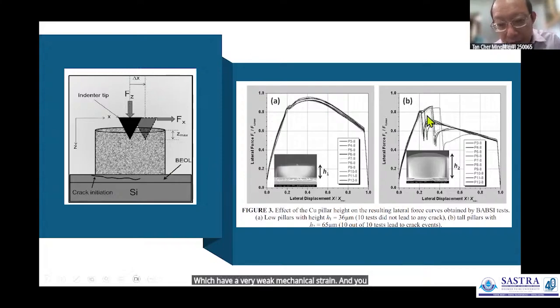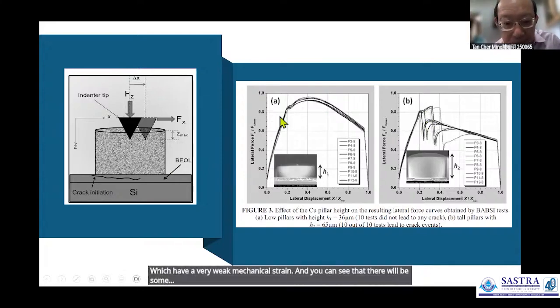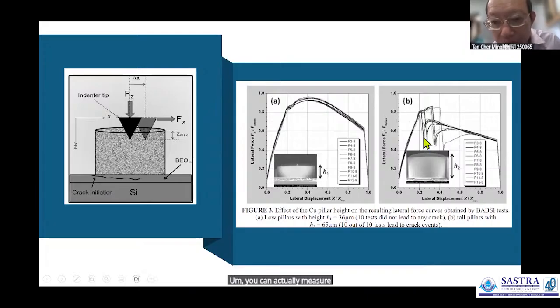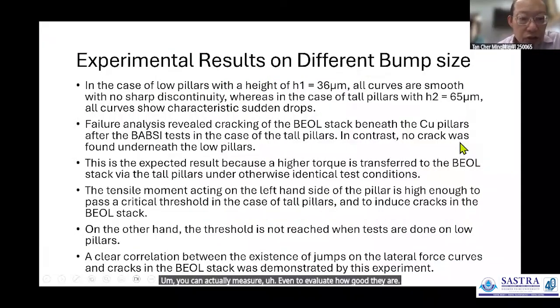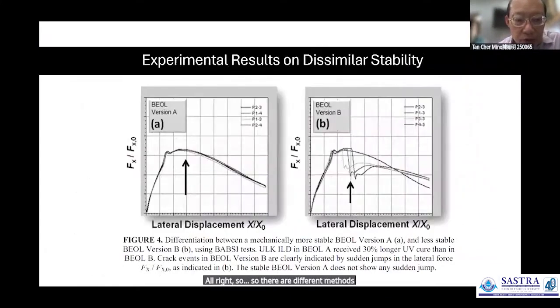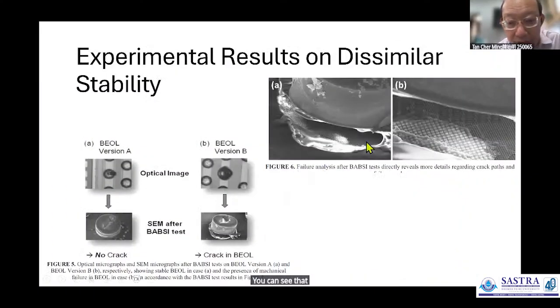And you can actually measure or even evaluate how good they are. All right, so there are different methods. I won't go through it. You can see that there will be a crack coming up, a failure, because of this crack even before the operation of the chip itself. It means that the moment you flip chip bond the chip onto the substrate, because of the force, you can cause a crack underneath the interconnect. And unless you lift up the interconnect, you wouldn't be able to see that. And this is actually happening.